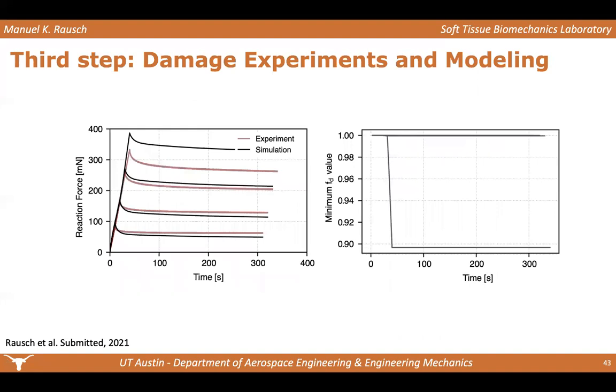And then finally, as a second form of validation, we predicted the stress relaxation tests completely unseen. So we didn't use this in the data information at all. And so we see actually pretty good fits for the 10%, the 20%, and the 30% strain, but then one data set just doesn't look right. And so I'm pretty sure that this is just an outlier in our experiments, right?